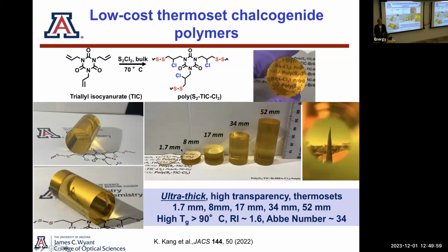And I got a couple more slides, again, of new things. We have a new material that's different from these materials that I was talking about. I didn't go into the chemistry, but it's a kind of messy process. You melt sulfur together with the organic monomer, and you need to have the monomer be miscible in the sulfur, and there are only very few monomers that actually are. We're fortunate to have some that are quite high performing.